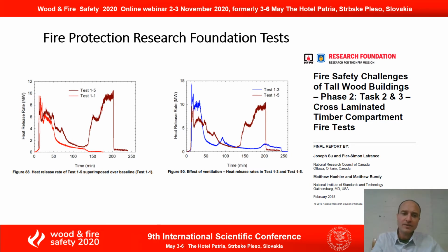But the opening factor has a huge effect on this. So you can see the blue curve there. That's the same one wall exposed, but with a bigger opening factor. And while you do get fire regrowth a little bit during these delaminations, it extinguishes itself more quickly.